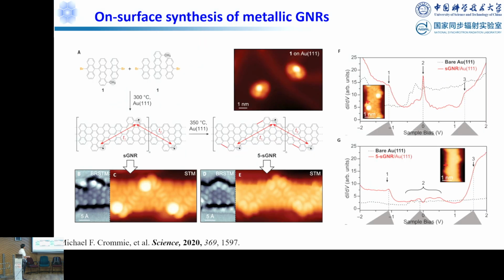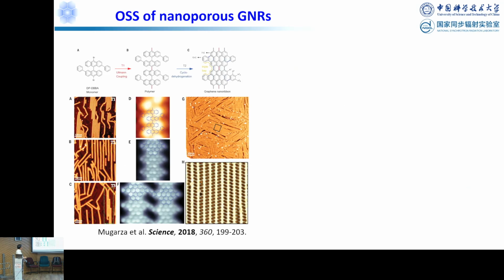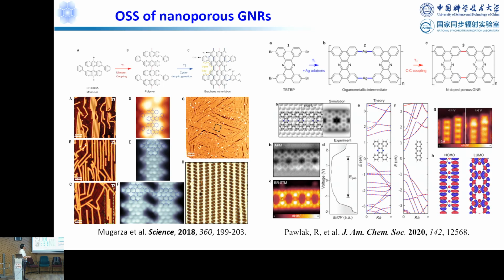And then you can also make metallic graphene nanoribbons on surfaces. You see here with these precursor molecules. This is from another group, and they use STS to demonstrate that it has metallic states here. This is also beautiful work. They take these precursor molecules first, the Ullmann coupling forms the nanoribbons on the surface, and then we further increase the temperature, the cyclodehydrogenation reaction happens, and then you introduce pores there. You can also synthesize porous graphene nanoribbons with nitrogen doping on surfaces.